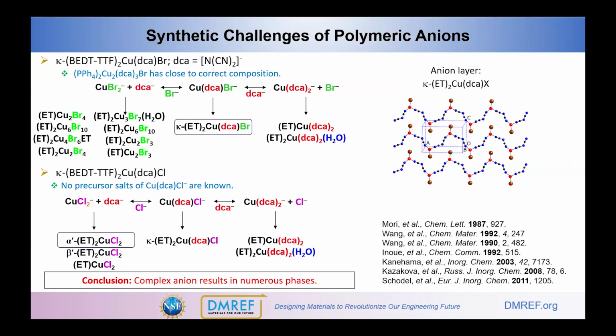The thing is that there's a lot of complications that go on when you try to do this electrocrystallization. In the case of copper dicyanamide bromide, you have an equilibrium between copper bromide and dicyanamide in solution that can get forced either to the right or to the left. The desired phase is the one in the middle, but you can make other phases depending on your stoichiometries in solution, like ET copper dicyanamide, or you can get phases that don't have any dicyanamide at all and get a lot of these copper bromide type phases. In the case of copper dicyanamide chloride, you have a similar equilibrium, but the equilibrium lies farther to the left. And so, at least in my experience, the predominant phase is more of these alpha copper chlorides, and then if you tweak things right, you can get the copper dicyanamide chloride crystals to form. So I think the conclusion is that these complex anions result in numerous phases that form, and so this needs to be better controlled if you really want to grow the crystals that you want.